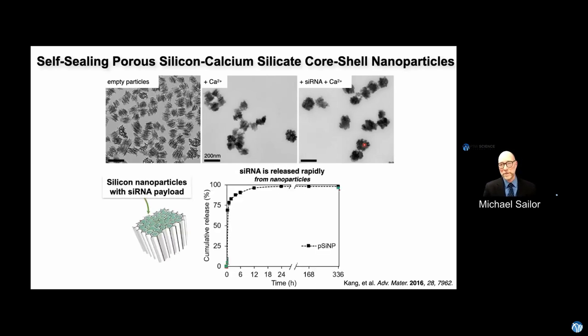Another question you might ask is, if you're making concrete out of this stuff, sidewalks don't dissolve in water very fast. And again, nanostructure. We were kind of surprised, very disappointed, in fact. We figured these things would be pretty stable. When you put these things into a buffer solution that's got the right pH for human body pH, shown here by the black dots, within an hour or two they're gone. So that was good in a way. Our particles do what we want them to do. They self-destruct, they dissolve, and they release their nucleic acid payload.